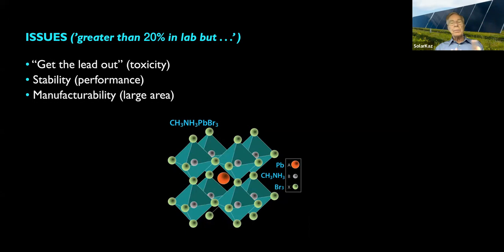Every technology has problems. I don't care what it is, whether it's renewables, there are also some limitations. I don't care if you talk about silicon, if you talk about perovskites. One thing is lead, but quite frankly, this is not just lead. It's lead held in this perovskite, hybrid perovskite, so it's more stable. The second thing is, quite frankly, there's very little lead in this very, very thin layer. Manufacturability, we're starting to see that it's not such an issue anymore. The remaining issue is still stability, as it is for every solar cell out there.